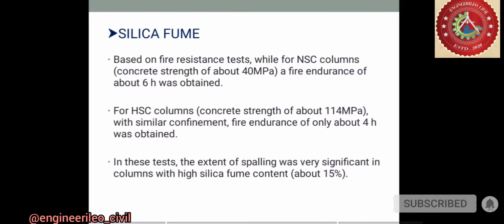Now we are going to see the silica fume. Based on the fire resistance test, for normal strength concrete columns, with concrete strength of about 40 MPa, a fire endurance is about 6 hours. For high strength columns, with a concrete strength of about 114 MPa, a fire endurance of only about 4 hours was obtained. In these tests, the extent of spalling was very significant in columns with high silica fume content, about 15%.